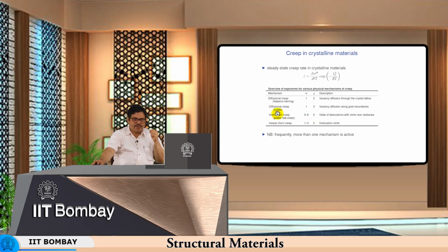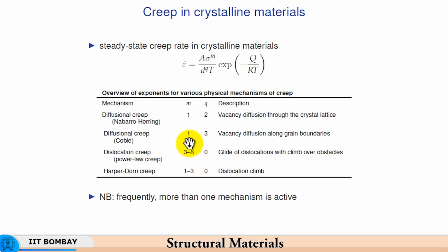Then here you have dislocation creep, which occurs at relatively lower temperatures, and you have glide of dislocations with climb over obstacles. Now, the effect of temperature is dislocation climbing over obstacles, and since the temperature is not high enough to eliminate all dislocation activity, there is dislocation activity present. Now, the grain boundaries are not as weak as they are in case of, say, diffusional creep, that is Nabarro-Herring creep. So, because the temperatures are relatively lower, the dislocation activity is also present, and therefore, m is of the order of 3 to 8.